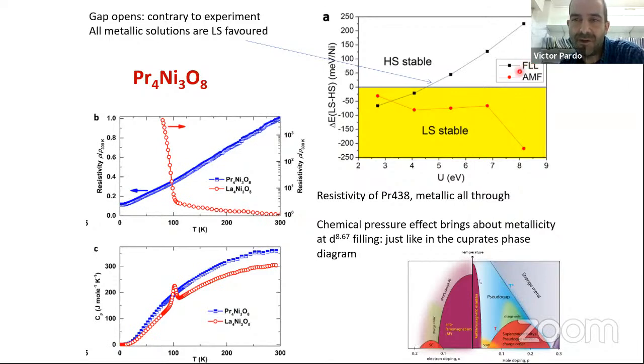And this other flavor, the so-called FLL, which is very commonly used, tends to favor the high spins. And in this case, at high U's, it does not coincide with experiments. And this is important to know for us doing calculations, to be able to make predictions when you don't have experiments available.